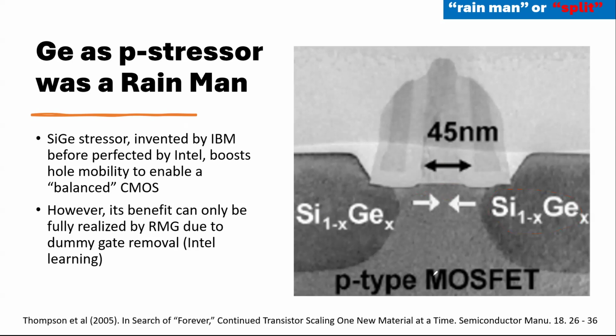There are two processes, okay? To get a complete Rain Man effect, the germanium in this case is obviously a stressor. You compress the channel by doing SiGe. You remove the silicon and put SiGe in, and then do this dummy gate removal. These two processes are needed to make it work. Otherwise, it won't work. If you don't have this process, it won't work. You get a little bit of improvement. That's it. That's not enough.